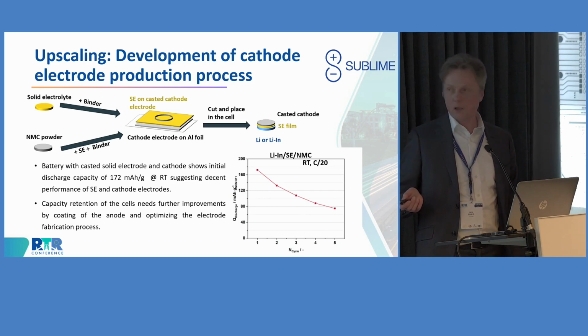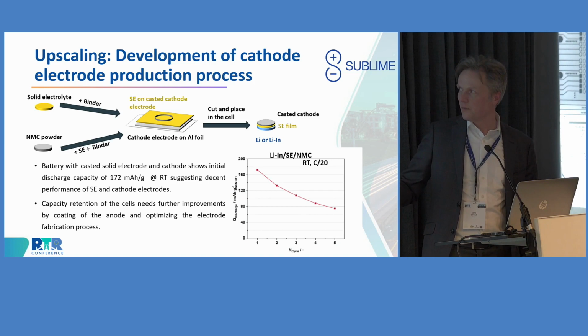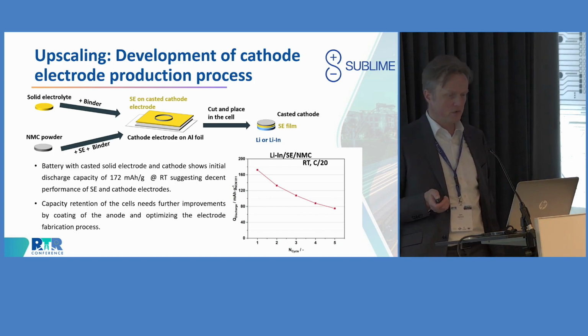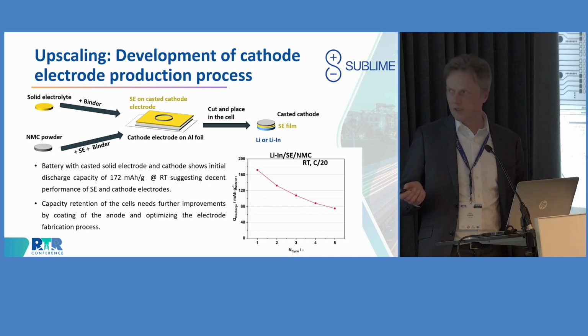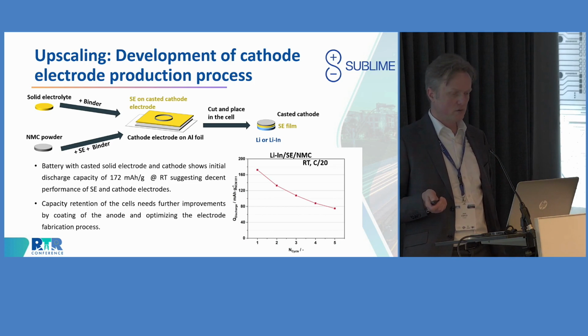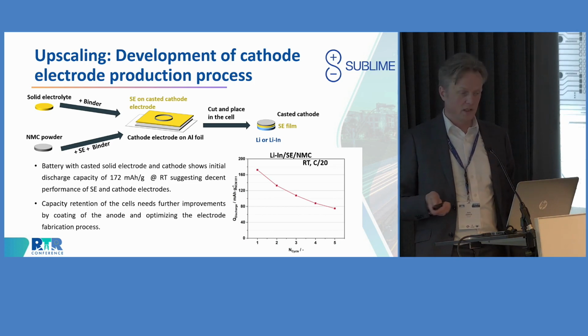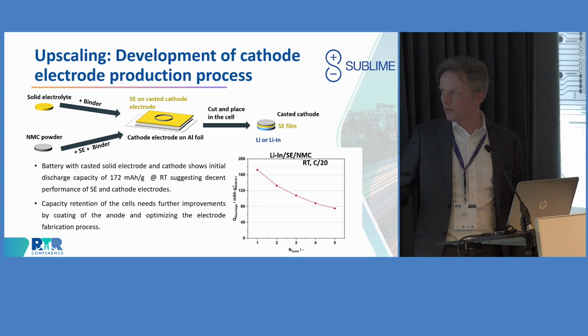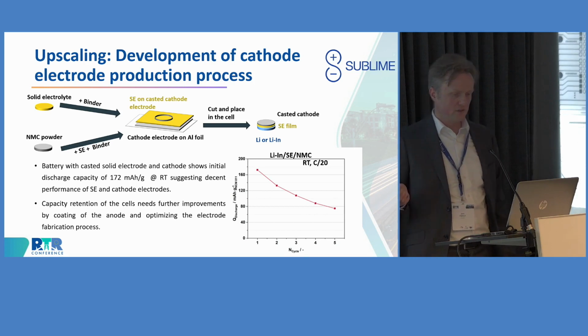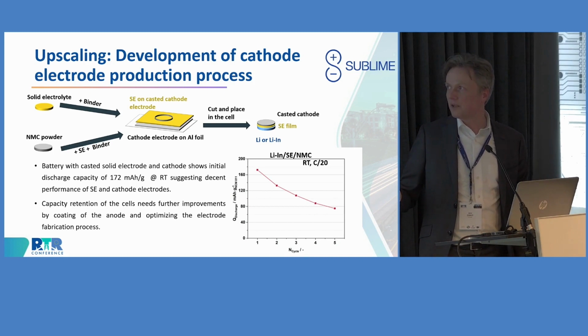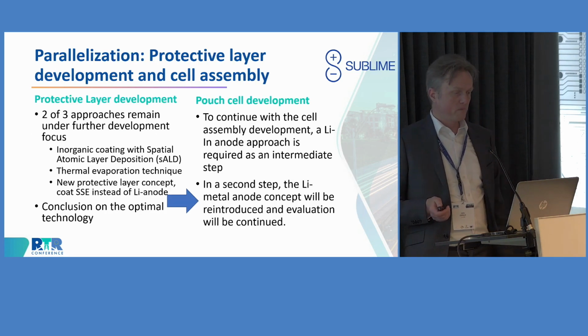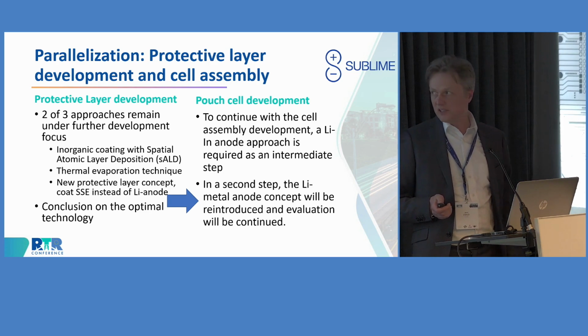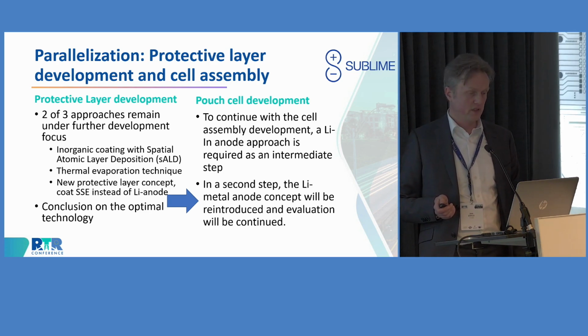So this is working. However, of course, because of the challenges that we see here on the anode side, we are using an intermediate step, exchanging lithium intermediately against lithium-indium in order to be able to continue on the optimization here. And once we have done that, then we would come back to the lithium. I will show this. So it needs further improvements, of course, but I think this is the way that we can do, and we still have 1 year ahead of us, so there will be still enough time to do the optimization here. Next step is in terms of the parallelization of these activities between the cathode and the solid electrolyte on the one side, and the anode.